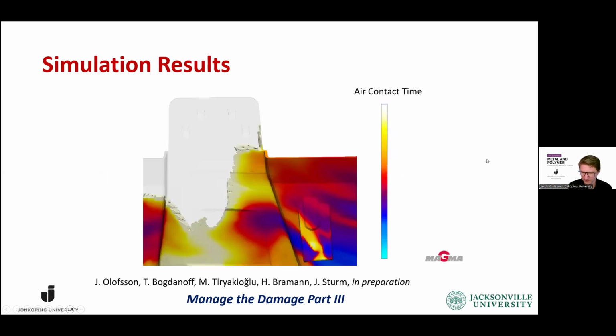And that was a bit of a struggle to realize: why is that? Why does this place fail differently than the other ones? In the simulations we first looked at the solidification simulation, to see if there's a difference in microstructure, but we didn't really see anything clearly. But when we went into the filling simulation and took a look at the measure called air contact time, we could see that there is actually something interesting going on in this region.